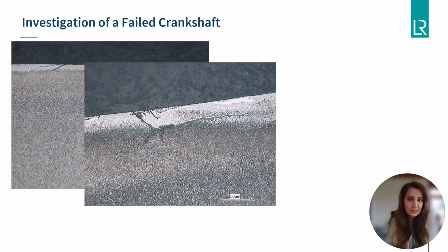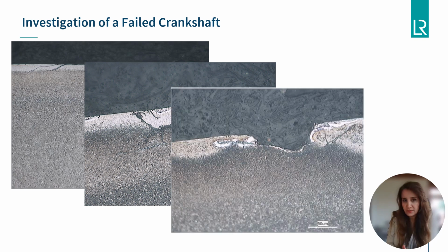However, the intermittent nature of the layer and its confinement to the areas of spalling indicated that the layer is attributable to wear. The white etching layer signifies a phase transformation from the quenched and tempered martensite into austenite and subsequent transformation into martensite during rapid cooling. To reach the austenitizing temperature, the material needs to be heated up to a flash temperature of 723 degrees centigrade.